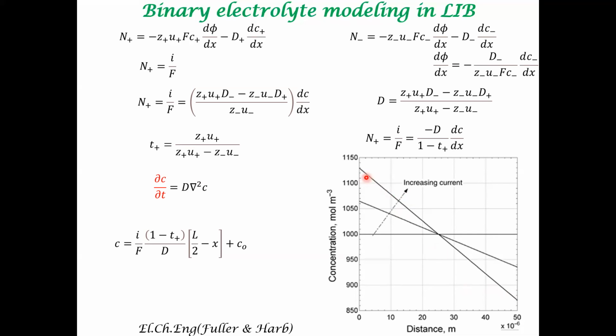Very high concentration at the anode might result in a mass transfer limitation associated with the salt that is to take up the lithium ion from the anode, and there can be very little Li+ in the electrolyte, because of which Li+ cannot be intercalated into the cathode. This is going to impose some potential penalties. We'll analyze this further in a subsequent lecture.